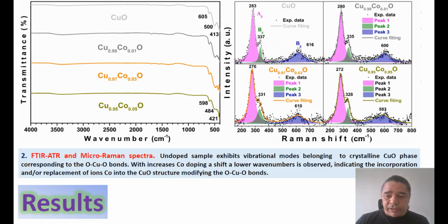Vibrational techniques. These techniques evidence that the undoped sample exhibits the typical vibrational modes belonging to crystalline copper oxide, corresponding to the oxygen-copper-oxygen bond. When increasing cobalt doping, a lower wave number is observed, indicating the incorporation or replacement of cobalt ions into the copper oxide structure, modifying the vibrational modes.